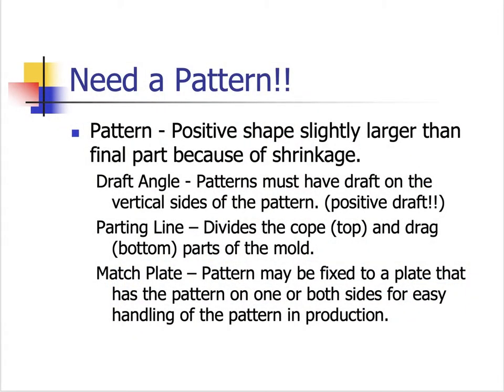Okay, the pattern itself needs to have draft on it. And what draft is, essentially, if I put something square, like a block, into the sand, and I just try to pull it straight out, what's going to happen is, the sand is pretty good in compression when all the sand grains are compressed together. But if you start pulling on sand grains, they'll fracture very easily. So in tension, the green sand is not very good. In compression, it's fine. It has a relatively good strength. So what we're going to need is a little bit of angle on the sides, kind of like ice cube trays. Okay, so if you ever made ice, getting it out of the tray sometimes is difficult, but it has a taper going up. That's called positive draft. If my pattern doesn't have positive draft on it, then my part's not going to come out of the mold.